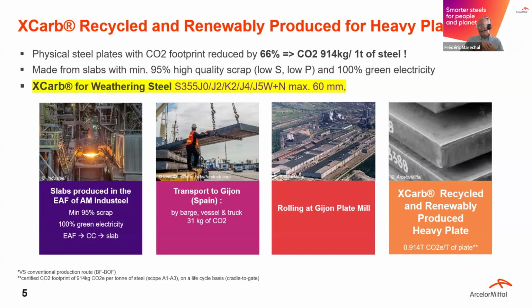So for every ton of steel that we produce, we generate 0.9 ton of CO2. And this is now about to be improved to close to 0.8 ton of CO2 in the new EPD that we will have released very soon. And this is mainly thanks to the production of steel out of slabs. So this is the prime material. And to get these results, we produce the slabs only with electrical arc furnace.